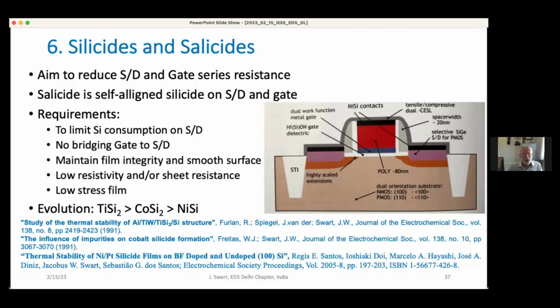metallization first happens over the spacer also, which is an insulator. And then you need to trigger the thermal treatments so that it doesn't form a silicide bridging the gate to the source and drain. So you need to design your process in order to avoid that. It needs to maintain integrity and a smooth surface, low resistivity and sheet resistance, and low stress film. In the 80s, people started with titanium, switched over to cobalt, and later on nickel silicides. And we followed all these three stages. We worked on these three types of silicides and had some contributions to the understanding and processing.